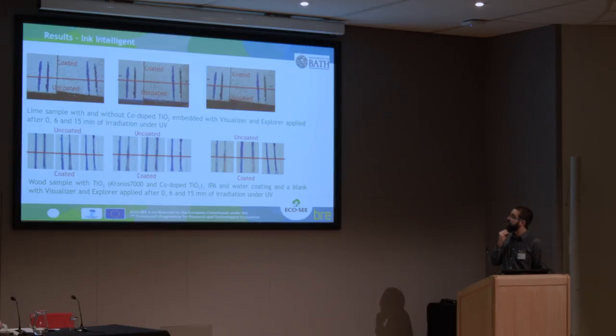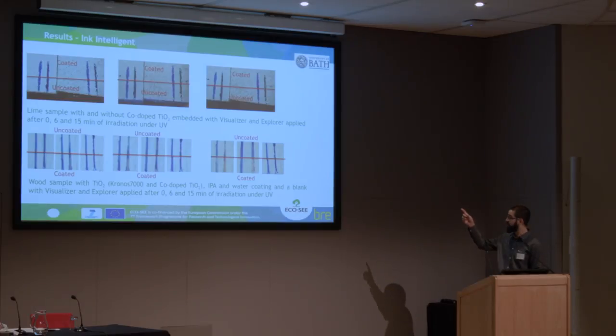These are the results from the coating tests. On the first row, you can see the lime sample. On the bottom one, you can see that we covered one part with aluminum foil to avoid irradiation and make a comparison between irradiated and non-irradiated areas. The first two samples in each row represent coatings with commercial particles and cobalt-doped particles. After 15 minutes of irradiation, you can see a really big difference between the coated and uncoated areas, meaning both coatings were photocatalytically active. The last sample is a blank to confirm that the dye is not self-degrading.